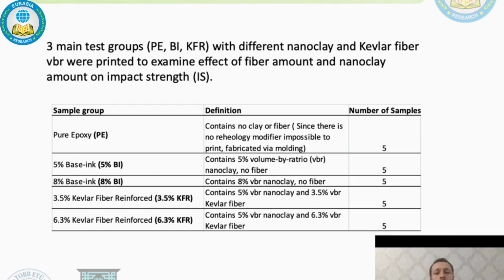To prepare a printable ink, enough rheology modifier must be used to both adjust the ink viscosity and to get that ink mixed homogeneously. So we prepared all the fiber reinforced inks with 5% nanoclay to make a good comparison between the base ink group and the Kevlar fiber group. In a similar way, the 6.3% Kevlar fiber group contains 5% nanoclay and 6.3% Kevlar fiber.